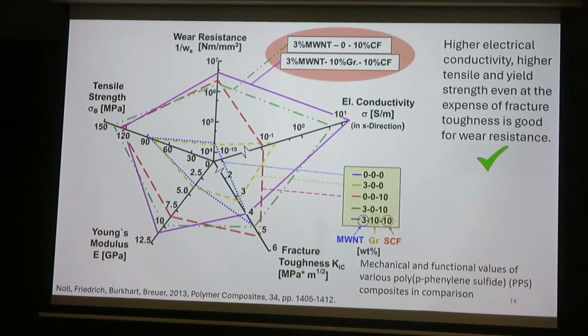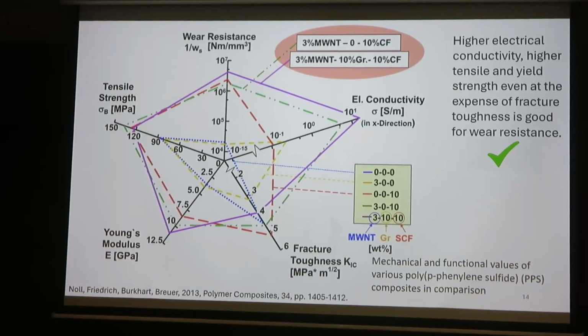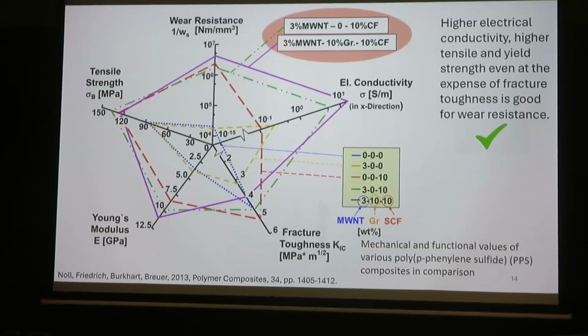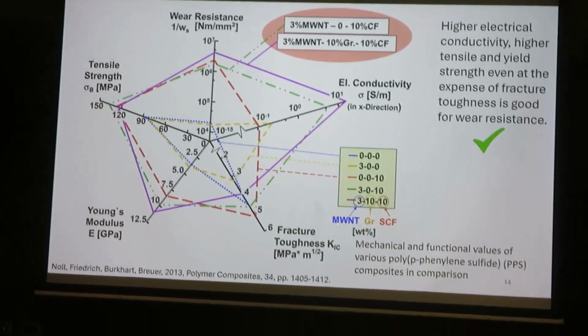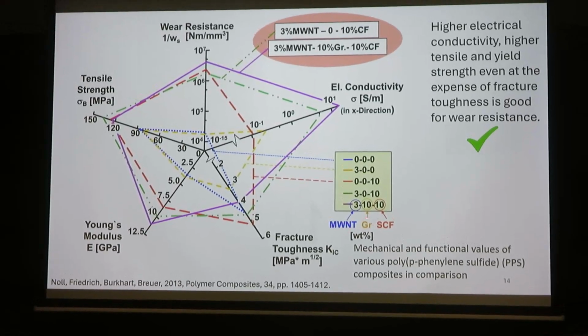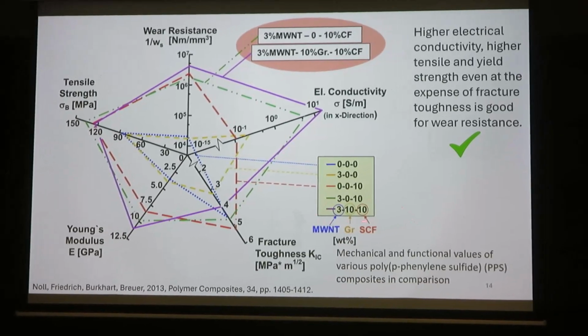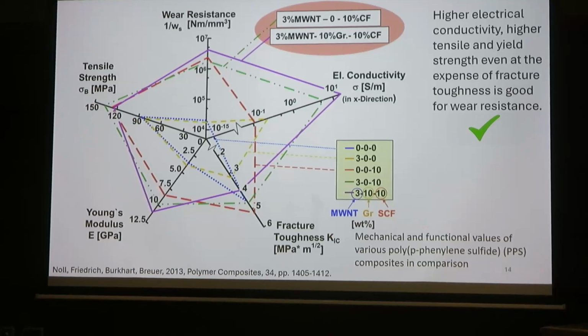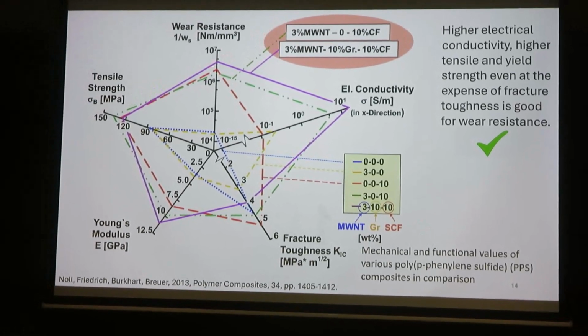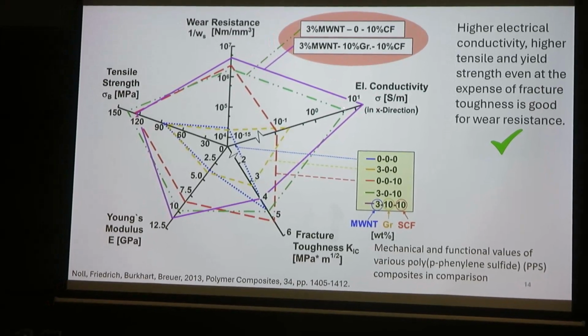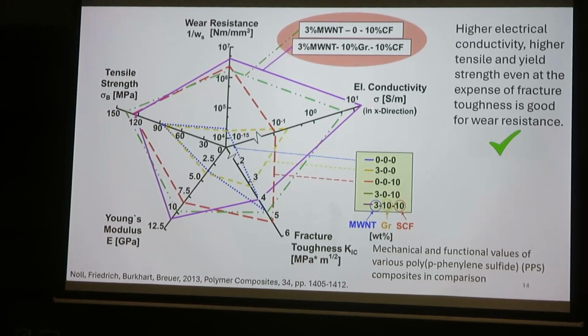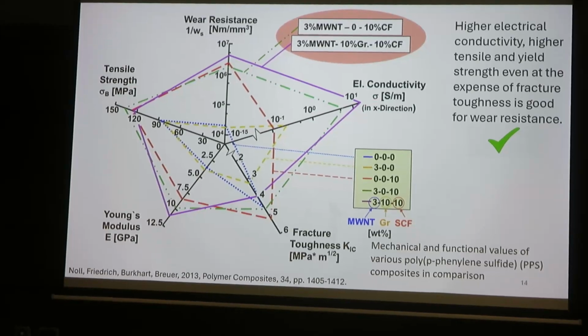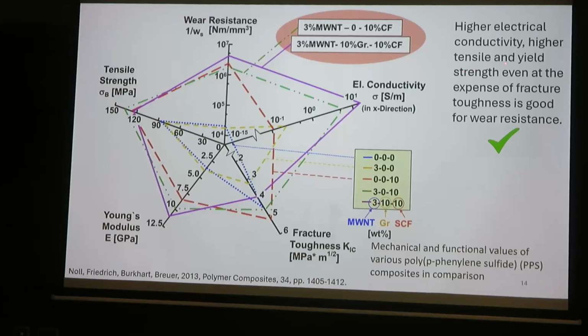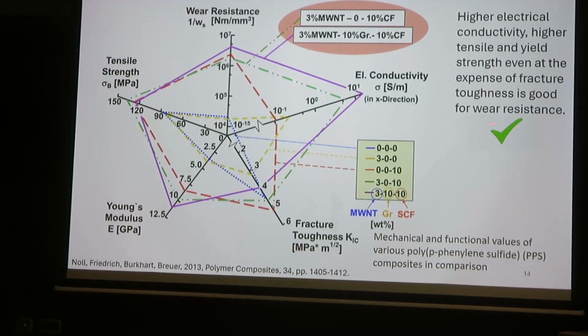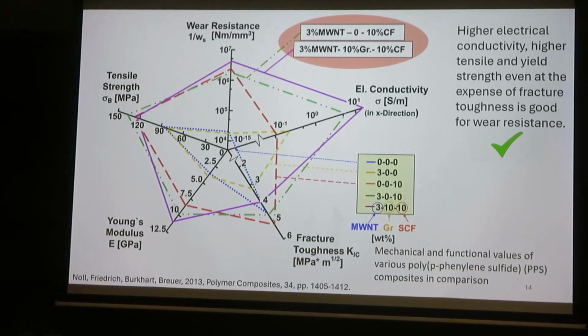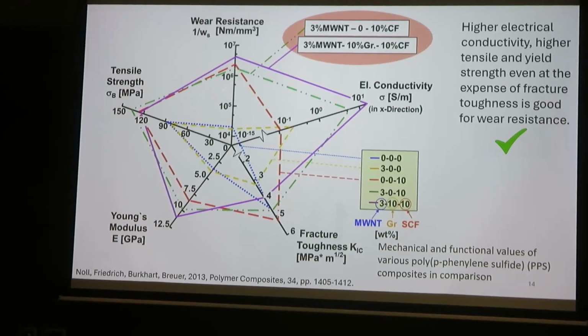So Friedrich and his co-workers gave this kind of what they call a spider map. Okay. So here you can see that for a material which has multi-wall nanotubes, graphite and short carbon fiber in these proportions, 3, 10, 10 weight percentage, it gives very good wear resistance, okay? But it also gives very good electrical conductivity, by which we can say that it has good thermal conductivity as well. So higher electrical conductivity, higher tensile and yield strength, even at the expense of fracture toughness, is good for wear resistance. So fracture toughness on this line is slightly lower, but all other properties are good, and it gives a very good wear resistance.